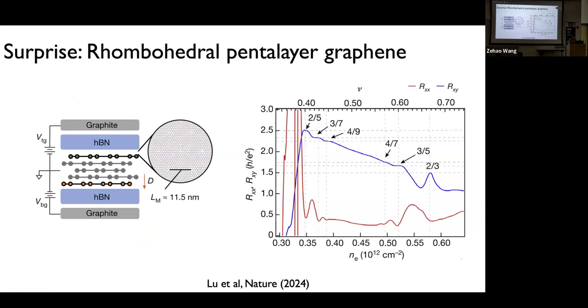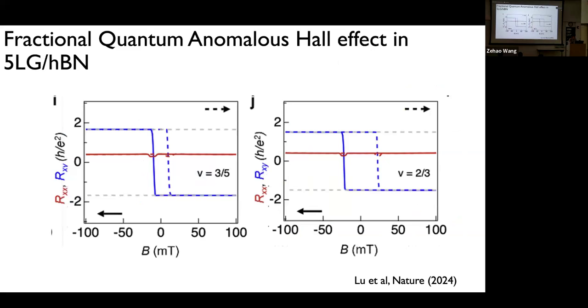Even more excitingly, a few months later, the group from MIT found that if you take a completely different material, 5 layers of graphene stacked in a very particular way called rhombohedral, which means that every time you stack, you shift half of a unit cell to the left, and you keep doing that instead of coming back. This is in contrast to what's called Bernal, where every 2 layers it goes back to the same place. Phenomenologically, things look extremely similar to what was measured in twisted MoTe2. And of course, this is the hysteresis.